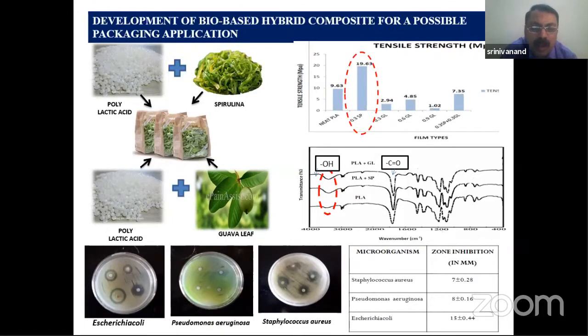So we thought of incorporating this spirulina and guava leaves. And to our surprise, what happened? The barrier properties have gone up. When we incorporated spirulina and guava leaves into PLA, we made a film out of it. And the film is capable of offering better thermal properties, mechanical properties, and barrier properties ideally required for industrial applications. So we were able to make some products out of it, and the products were found to be very stable as well as very robust and high performance.